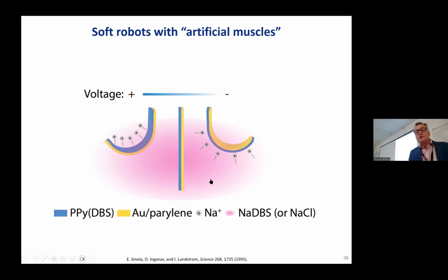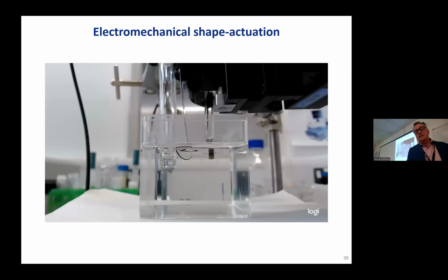But there are other modes of actuation as well, including electrical actuation. This is shown here. These used to be called artificial muscles. It was a field that boomed in the 80s and 90s, and then it dropped off. But now it's slowly coming back. And the idea is to combine a very thin metal film with a conducting polymer. This is a material that can uptake ions from an electrolyte if you apply a suitable potential and swell. And as it swells, it can change the shape of this bilayer structure. So if you engineer it well, it can do really interesting acrobatics. So this is a bilayer that opens and closes under the actuation by a small voltage.